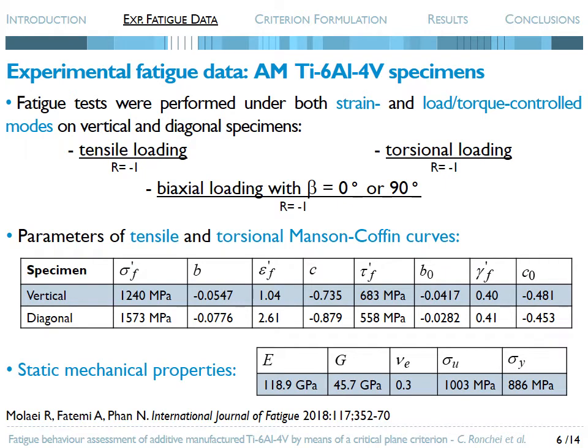Fatigue tests were performed under both strain control and load torque control modes on vertical and diagonal specimens. The experimental loading conditions consisted in tensile, torsional, and combined tensile-torsional loading with a phase shift beta equal to 0 or 90 degrees, with the fatigue ratio R equal to -1. The parameters of the tensile and torsional Manson-Coffin curves were derived from the uniaxial fatigue data as listed in the table on the top. Moreover, the static mechanical properties derived by means of static tensile and torsional tests are reported in the table on the bottom.